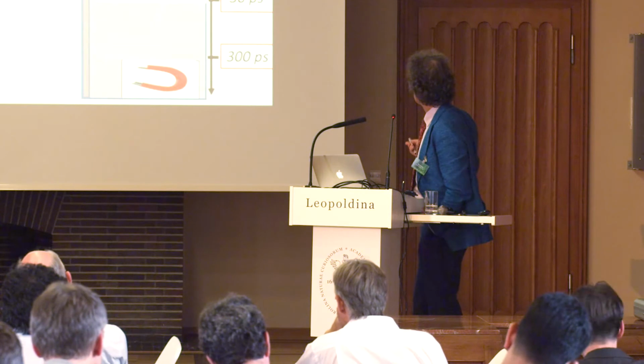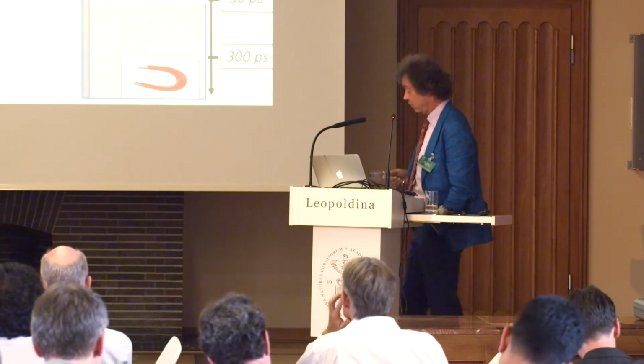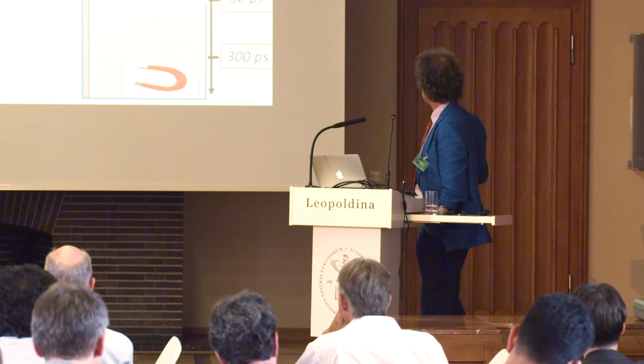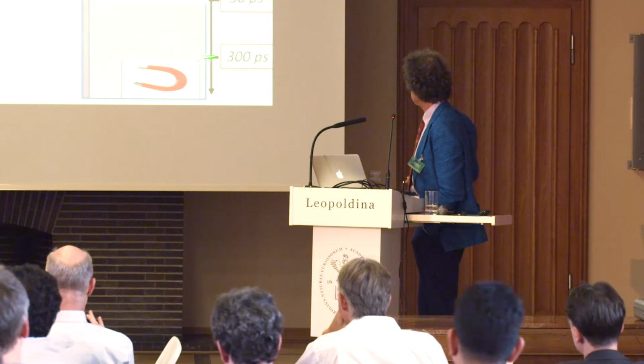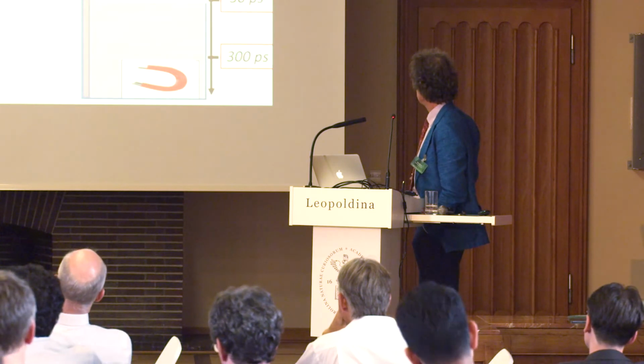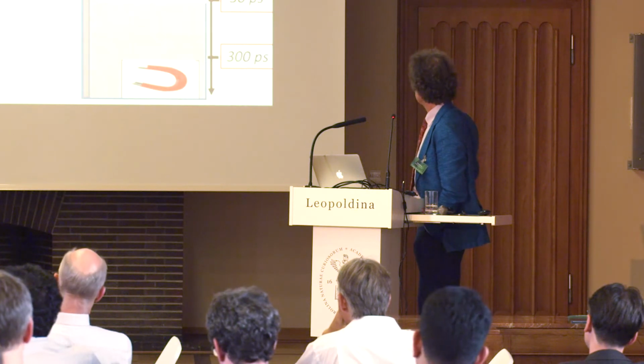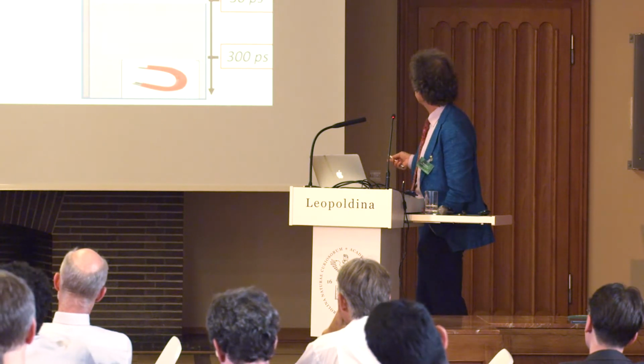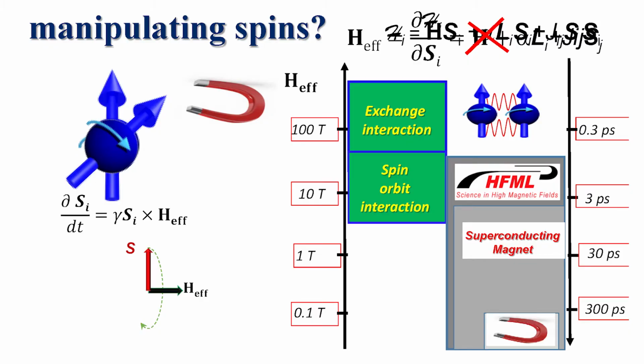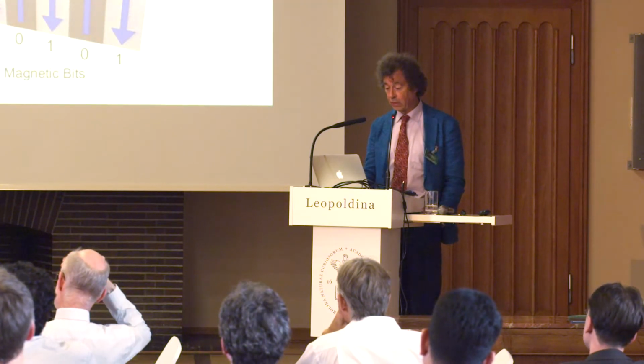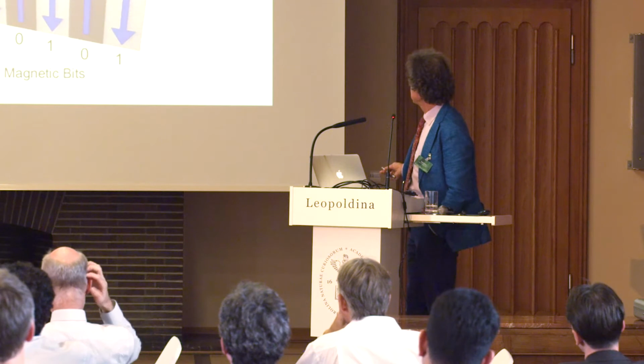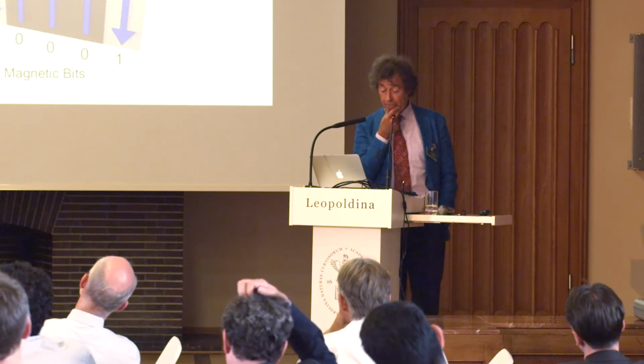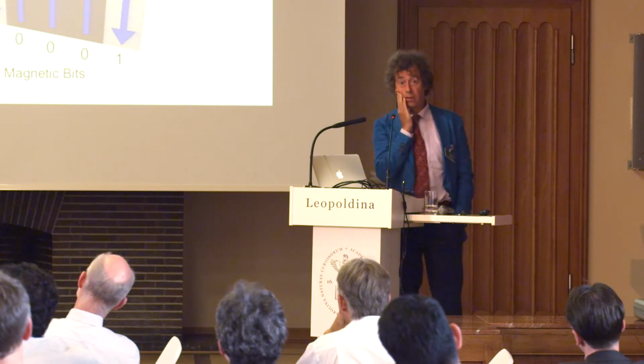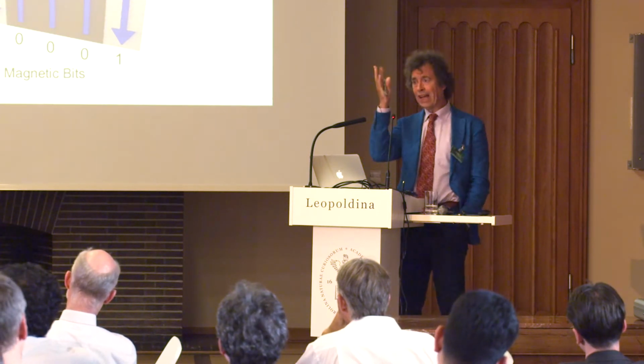And then here you have the time scales related to these strengths. If you think about normal fields and magnetization dynamics and precession, then you're talking about nanoseconds, 300 picoseconds. But if you're thinking about very strong fields, then you're talking about sub-picoseconds and femtosecond timescales. And so this is what we started to do. The idea is magnetic recording. Normally you do that with a field. You have a short pulse, and then you reverse a bit. And that takes, like I said already, 0.1 nanojoule and around 1 nanosecond in time.